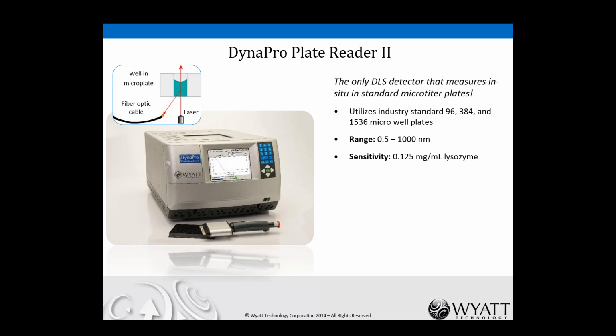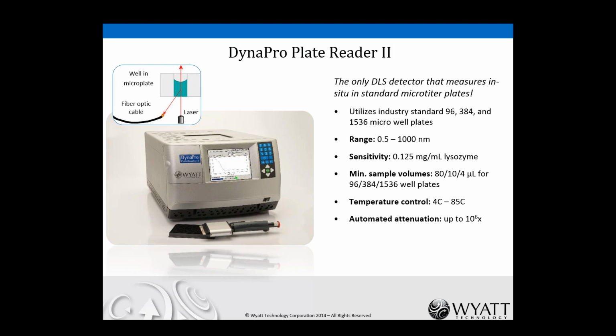In terms of sensitivity, it can go down to about 0.1 mg per mil of lysozyme. Lysozyme is a protein with a molecular weight of 14.4 kilodaltons, and the sensitivity scales with molecular weight. So for instance, an antibody with about 10 times the molecular weight will have about 1/10 the minimum concentration for sensitivity, so it would be 0.01 mg per mil of an antibody. Minimum sample volumes, of course, depend on the particular plate that you're using. So if you're using 1536 well plates, you can go down to as little as 4 microliters of sample. More typical would be 384, where you're using maybe 20 on average, or 10 if you want to push it.